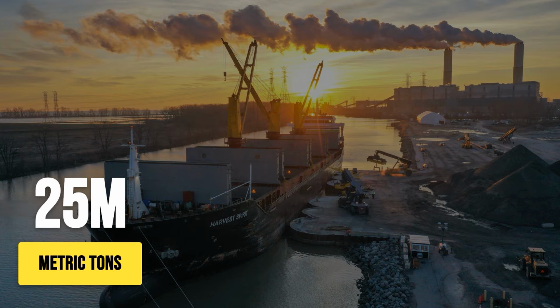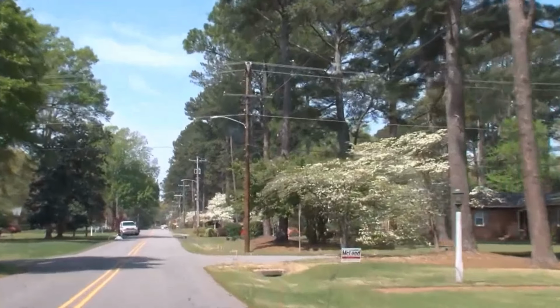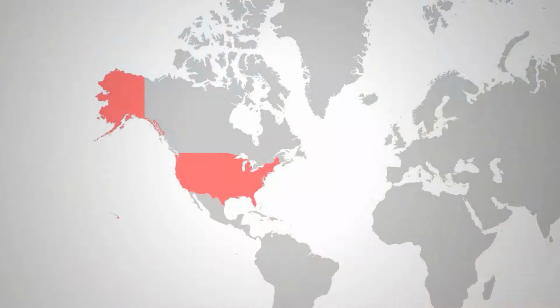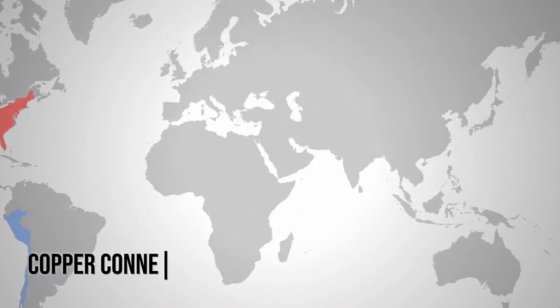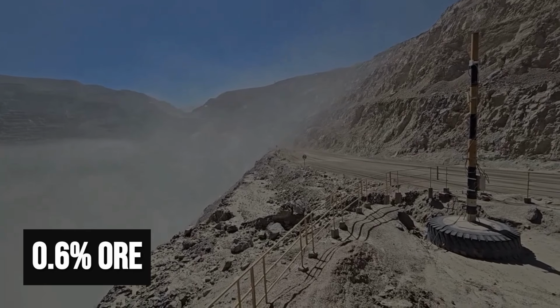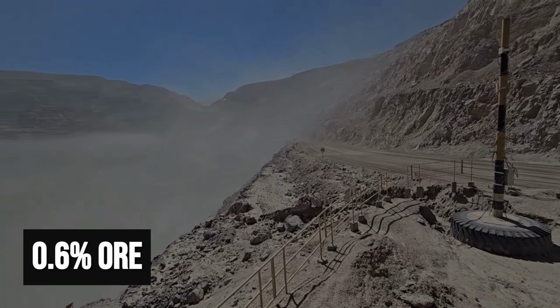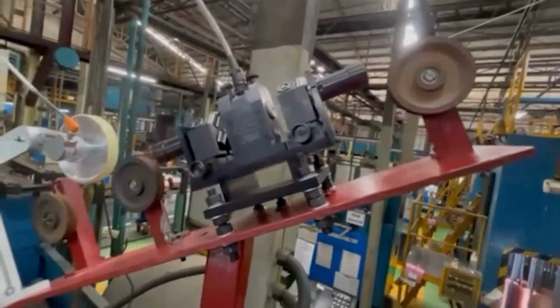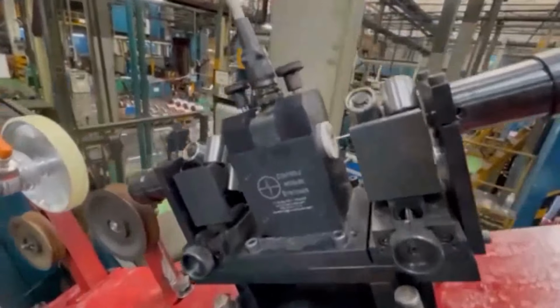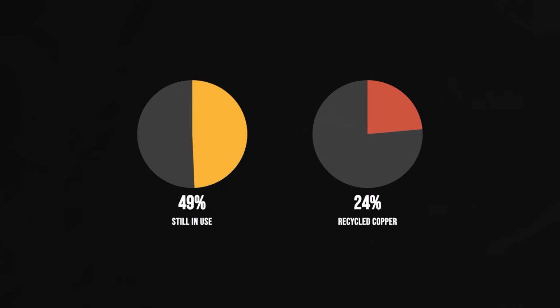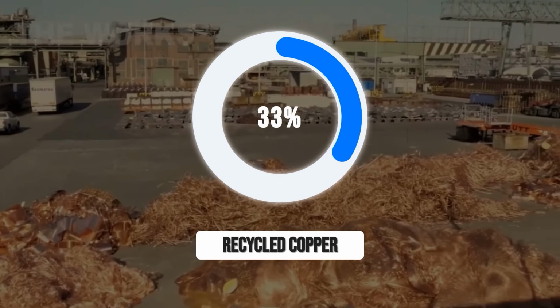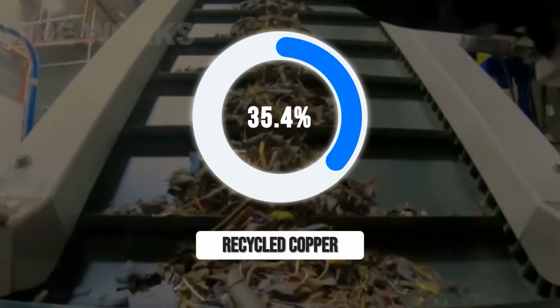Every year, over 25 million metric tons of copper are mined, refined, and shipped worldwide, powering cities, industries, and daily life. This documentary has shown how copper's journey spans continents, from ore grades as low as 0.6% to finished wire tested for 100% conductivity. About 49% of all copper ever mined is still in use, thanks to near-perfect recyclability and a global recycling rate now exceeding 35%.